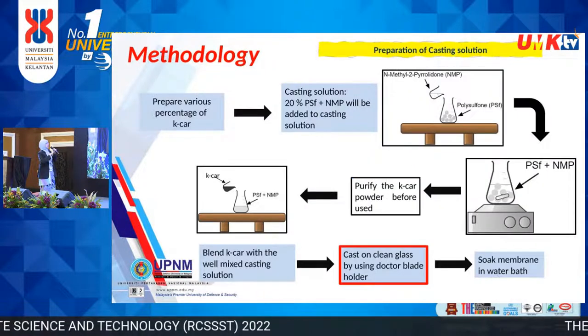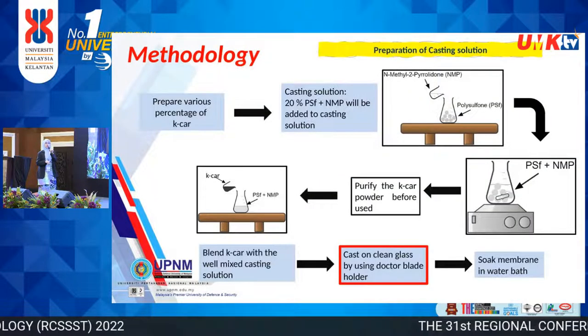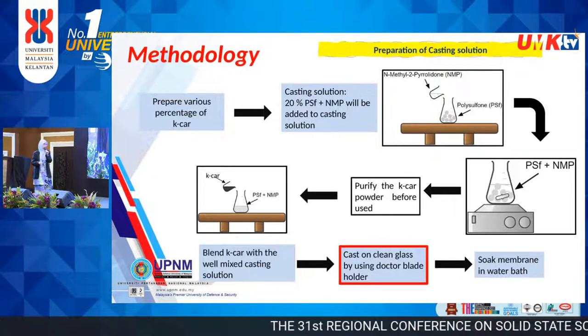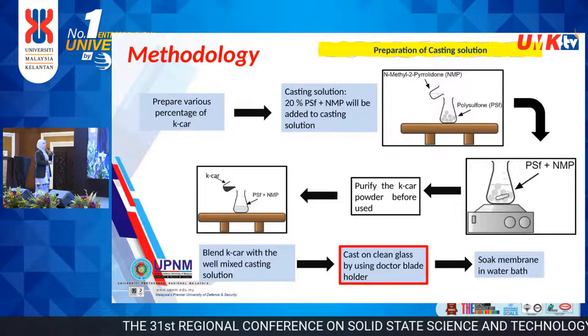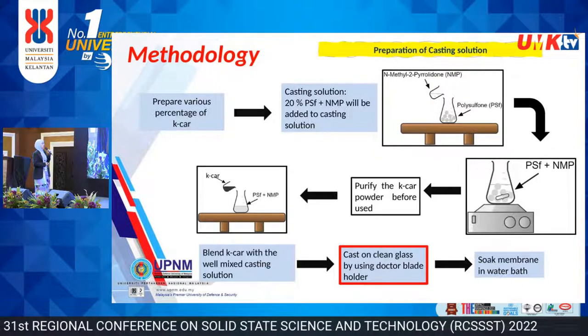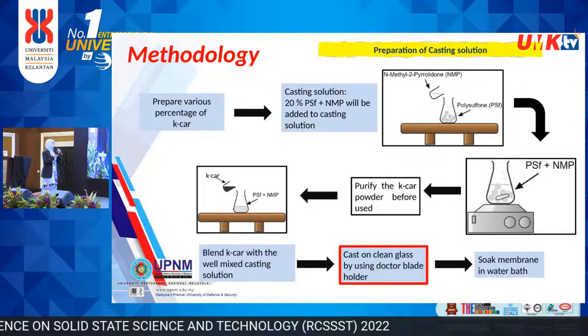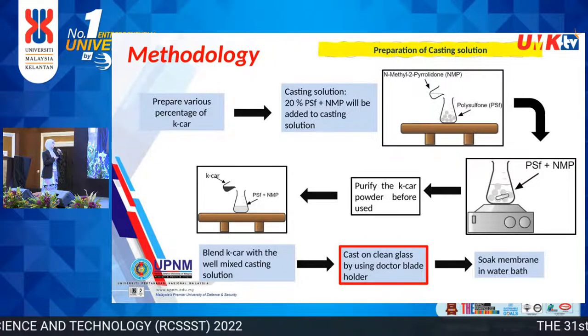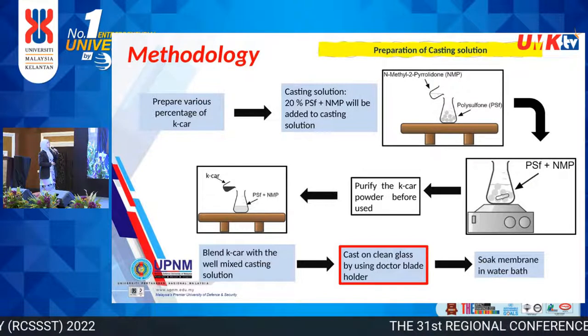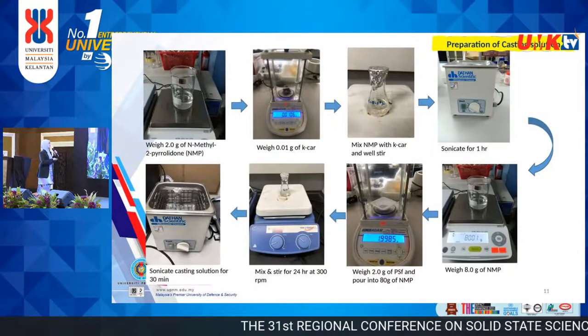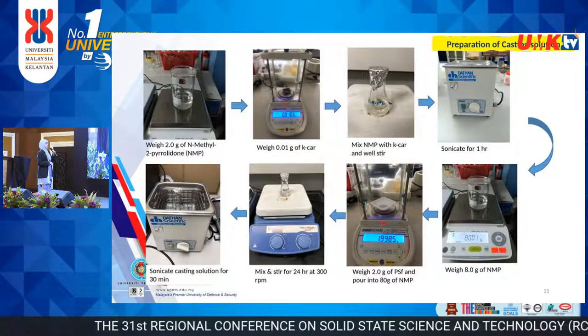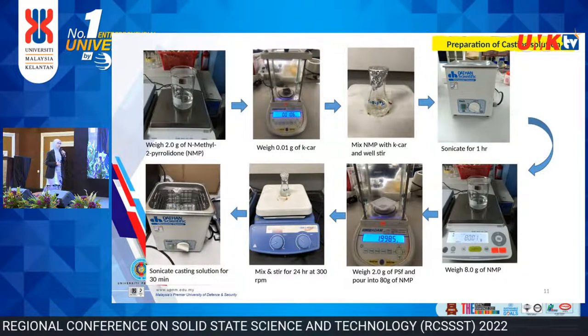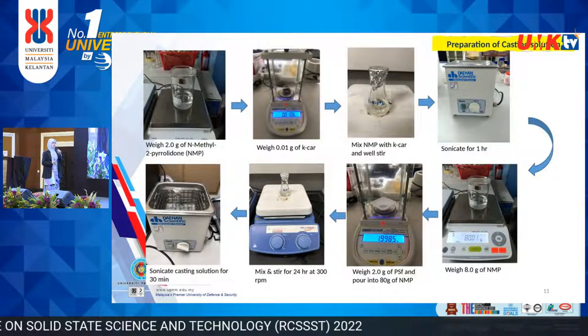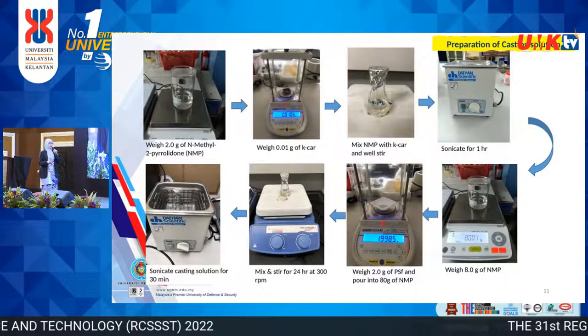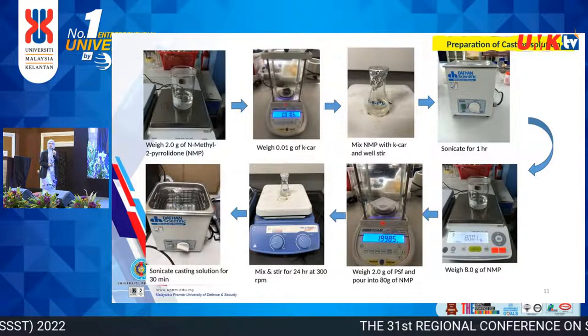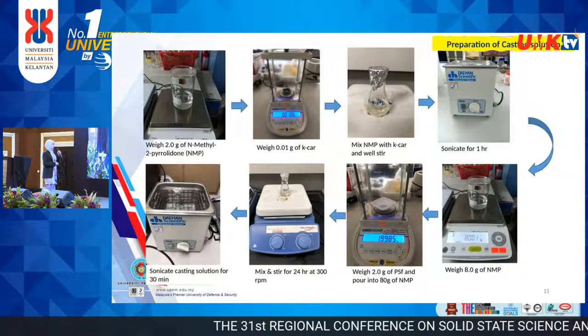All right, so these are the steps to prepare the casting solution in order to fabricate the membrane. Basically we need to prepare the materials, whereby we have kappa carrageenan and also the polysulfone resin. We prepare them at an appropriate percentage ratio. These are a few figures of what we do in our lab. To fabricate the membrane, it normally takes more than one day, because we have to prepare the casting solution first and leave it overnight, and then the next day only we can fabricate the membranes.